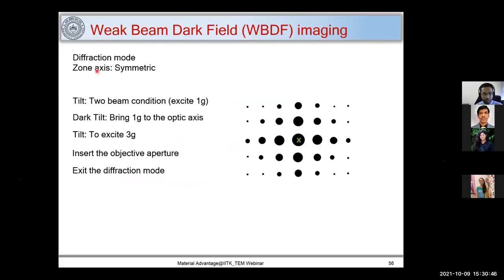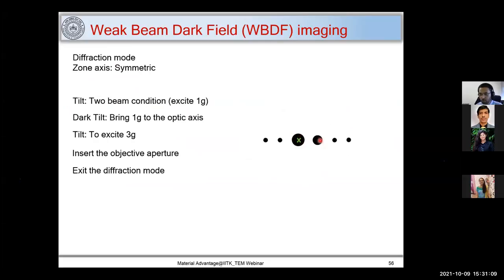So here you first get to a diffraction mode, get to a zone axis, and get a symmetric diffraction pattern like this. Okay, and this cross represents your optic axis. Now tilt to 2 beam condition. So go to 2 beam condition or excite 1G. So what I'm going to do is make the intensity of this spot more and this spot more only. So you get these 2 brightest spots. So this is our 2 beam condition.